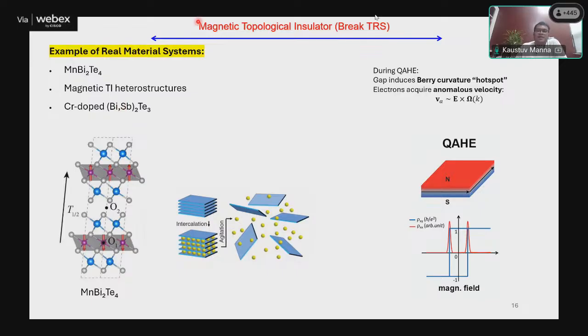Now, what is the other part I'll go into? What is the consequence when you gap out one edge state? Because in the topological insulator, you had two different edge states, one associated with the up spin, another from the down spin. Now, by artificial means, you are gapping out one edge state. What is the consequence of that? Mathematically, inside the topological material, what is going on? Inside the material, when an edge state gaps out, what it gives rise to is called the Berry curvature. It introduces a Berry curvature hotspot in the compound.